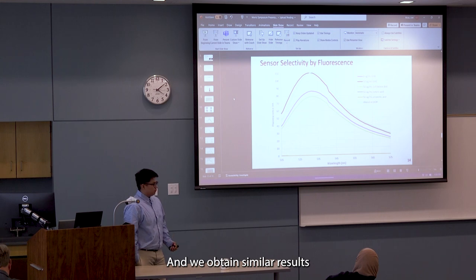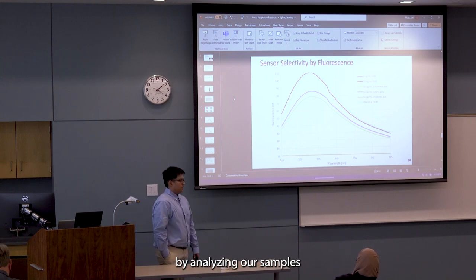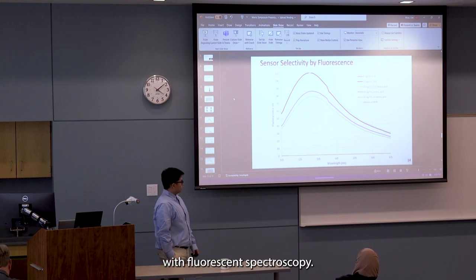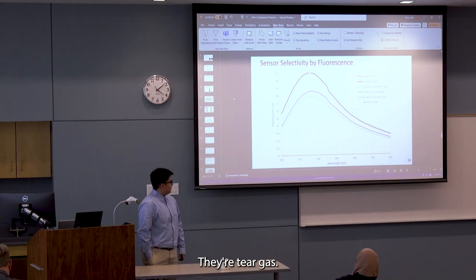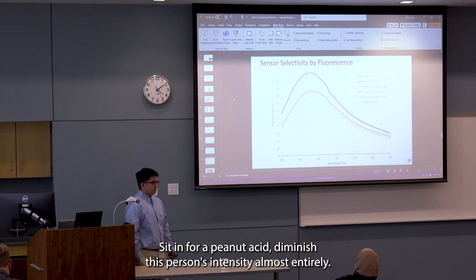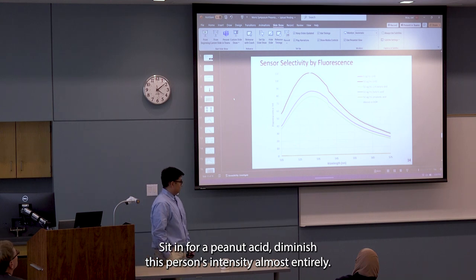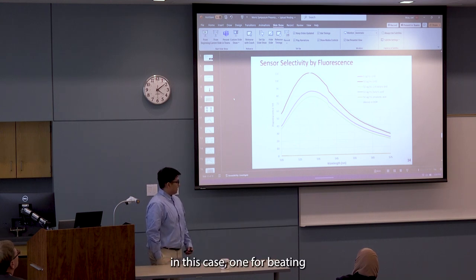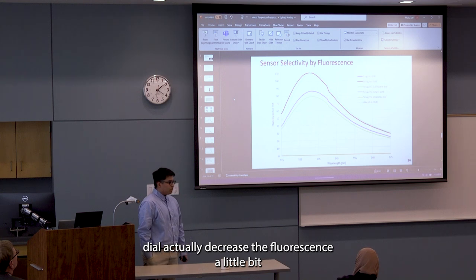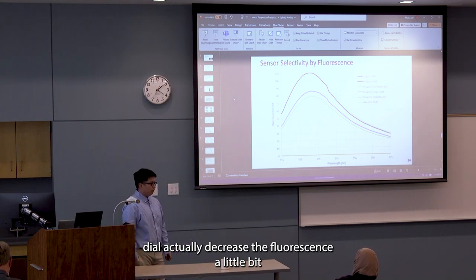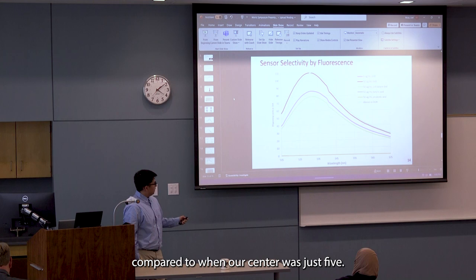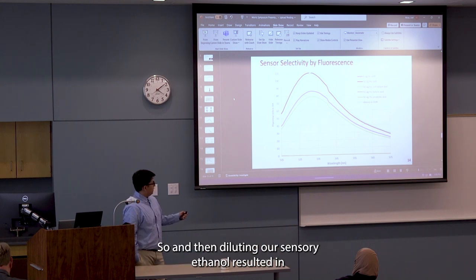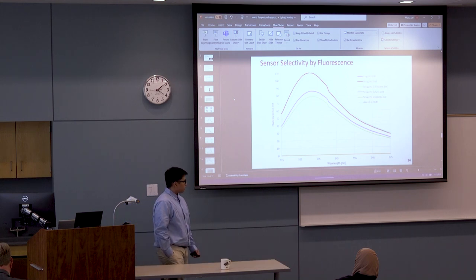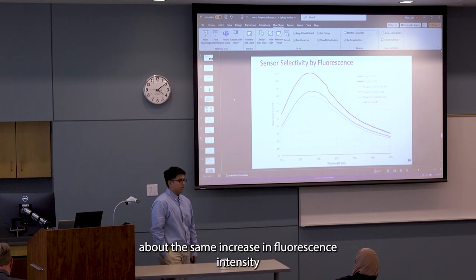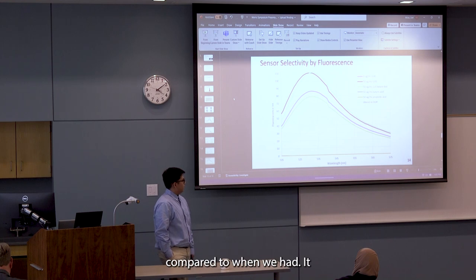And we obtained similar results by analyzing our samples with fluorescence spectroscopy. The butyric acid and propionic acid diminish the fluorescence intensity almost entirely. In this case, 1,4-butanediol actually decreased the fluorescence a little bit compared to when our sensor was just by itself. And then diluting our sensor in ethanol resulted in about the same increase in fluorescence intensity compared to when we had GHB present.